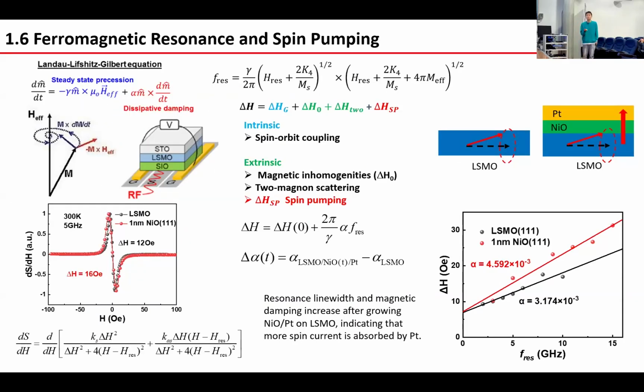Then I will introduce some concepts of ferromagnetic resonance and spin pumping. In the real measurement in this figure, we face down the sample in contact with the coplanar waveguide and excite the RF field along this direction and sweep a magnetic field along the perpendicular direction. And when the magnetic material absorbs the energy and reaches the resonant condition, the ferromagnetic resonance dynamics can be expressed by the LLG equation, containing the steady state precession and the dissipative damping. The first term is the magnetization precessing around the effective field, while the second term lets the magnetization relax toward the effective field.